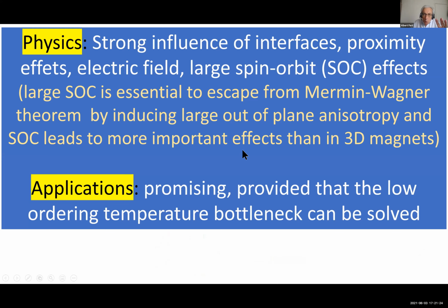So I begin with a few words, general words, on the physics of these 2D magnets. First, as for any very thin layer, there is a strong influence of interfaces. Interfaces are more important than what is between. So this leads to an influence of proximity effect. The property can be controlled by the proximity with another material. This is a flexibility that is very interesting. And because with a very small voltage, when the thickness is small, you can generate a large electric field, you can also control the property significantly by electric field.